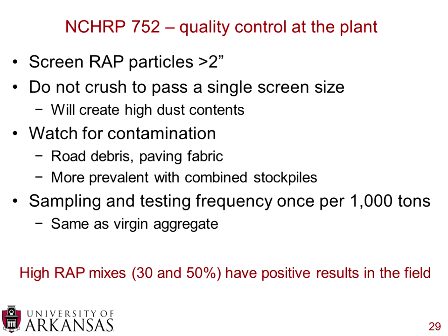So for NCHRP 752, I've been talking a lot about the importance of quality control at the plant, and here are some actual details on what needs to happen. First, they recommend that any RAP particles that are greater than 2 inches in size are screened off. And as you're screening these materials, they also recommend you do not crush to pass a single screen size. So if you're targeting maybe a 1-inch nominal maximum aggregate size, they do not recommend that you just cycle material constantly through a 1-inch crusher. Because what will happen is you'll get a very high dust content, and you'll really dilute the benefit of using RAP. They recommend instead that you step down.